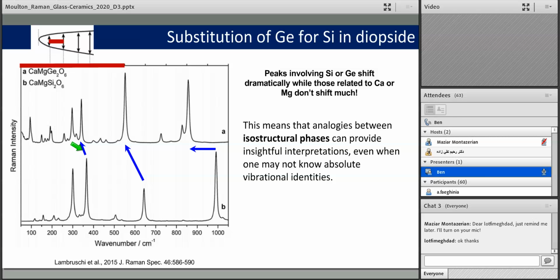And so I want to make two points here. One is that the masses do have a strong effect on the vibrational modes, which means you can use this if you have substitution, for instance, of iron for magnesium in your phase. And two is that even with quite different compositions, if they are isostructural, you can transfer insights from one structure, for instance germanate, to a silicate, if they have the same profile. And of course, there are some other subtle differences, but we will take it easy for a moment.